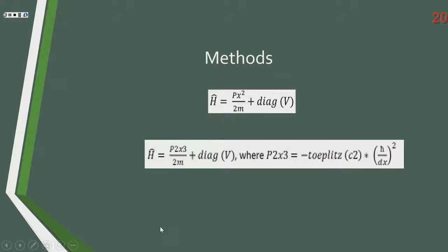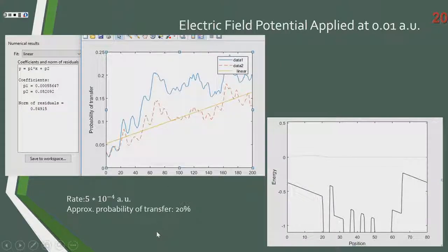These are the two methods I used, which are different methods to calculate the Hamiltonian. And then these are the results I was able to obtain. This was at an electric field strength of 0.01 AU, which you cannot see because it's behind the video. But data one and data two, the blue line and the red line, represent the two different methods. And the yellow line is a linear slope to determine the rate that was obtained. P1 being the rate, and in this case, 5 × 10⁻⁴, with approximately a 20% transfer.